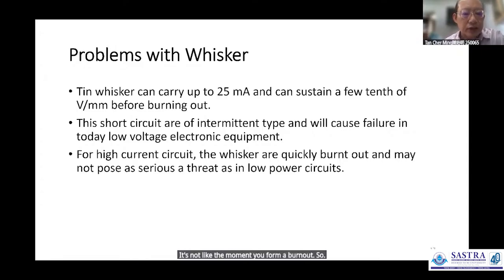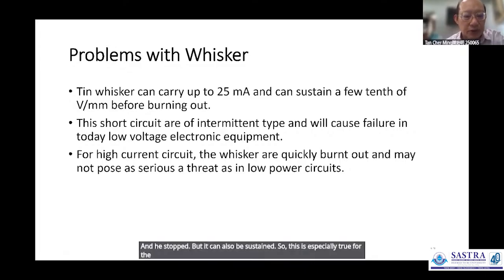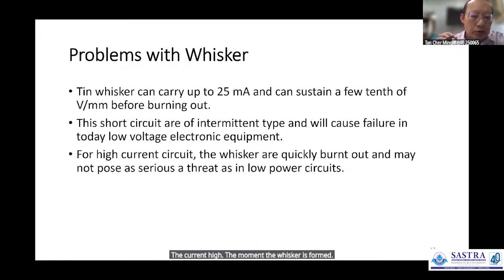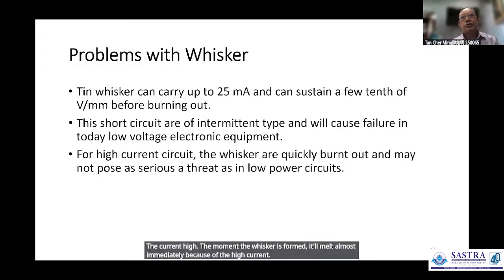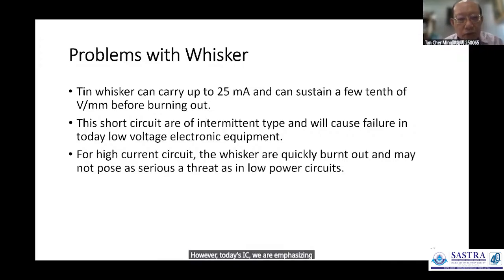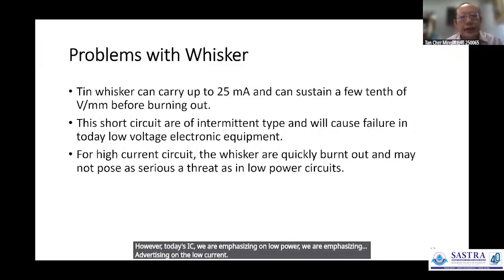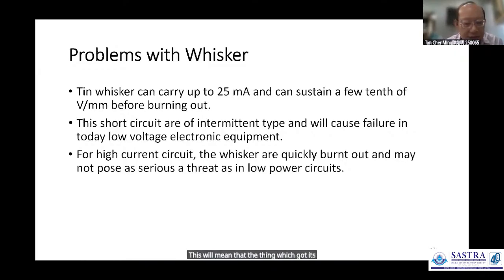When it carries the current, it causes a short circuit. And this short circuit can be intermittent, because the moment the current passes through, it melts and it stops. But it can also be sustained. This is especially true for low current circuits, because for a high current circuit, the moment the whisker is formed, it will melt almost immediately because of the high current. However, in today's IC, we are emphasizing low power. We are emphasizing low current. This will mean that the tin whisker that is formed will be sustained, and therefore it can actually pose a very serious threat to the low power circuit.